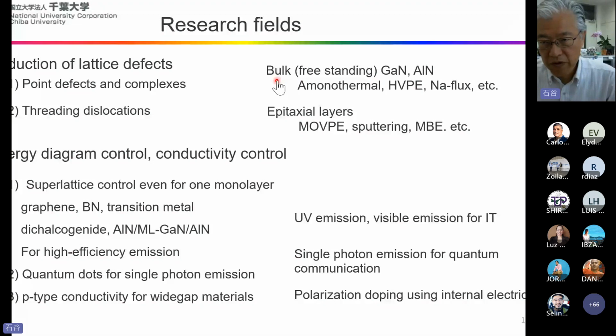For bulk growth, ammonothermal, HVPE and sodium flux and some other methods are being applied. And for epitaxial layers, MOVPE, sputtering, and MBE. Mainly MOVPE and MBE have been conventionally researched, but most of the mass production was conducted by MOVPE. But now sputtering is found to be a very good method. It's good for fabricating the high energy gap materials of gallium nitride, aluminum nitride, and so on.